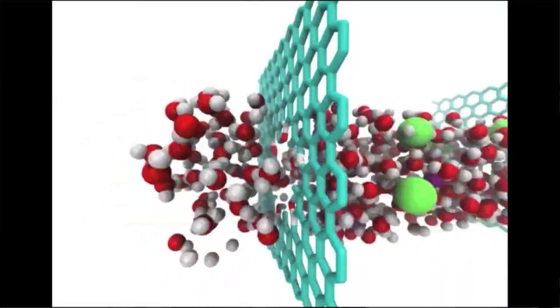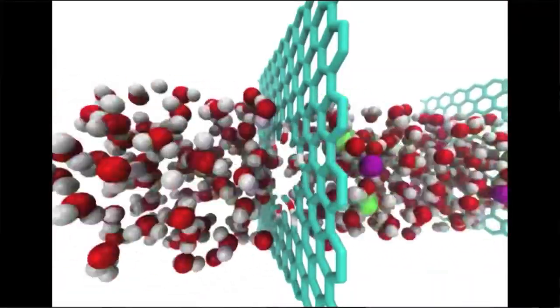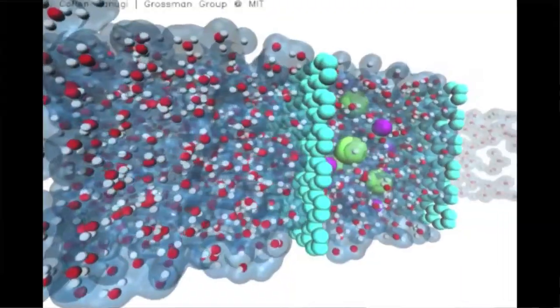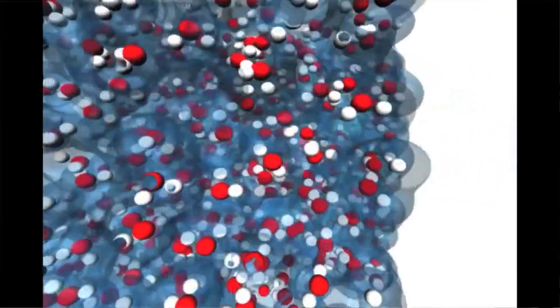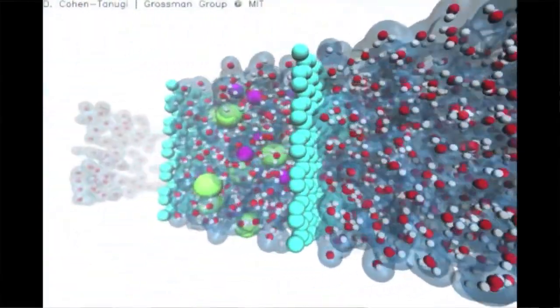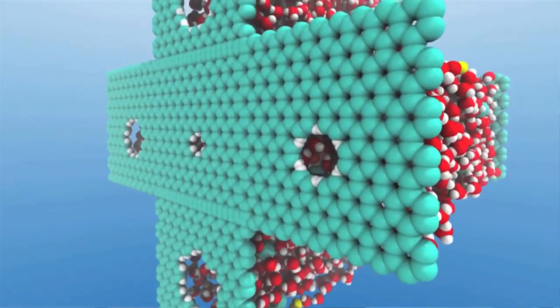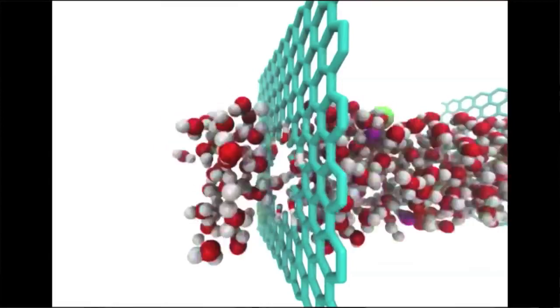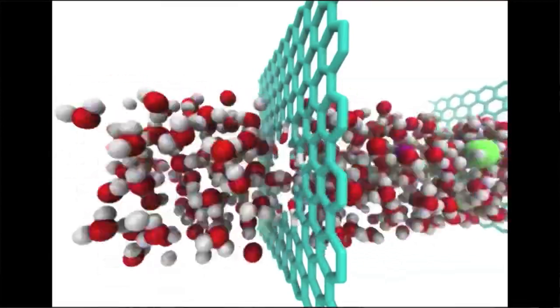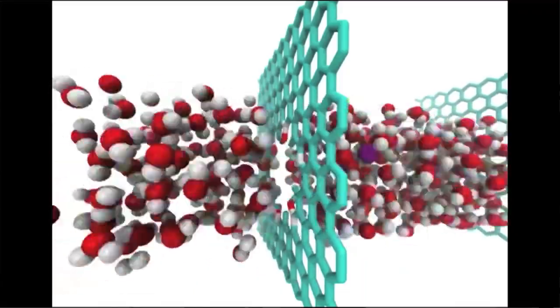Graphene oxide was shown by Rahul in the physics department here to have high permeability to water, but to be an effective barrier to all kinds of other things. One of the ideas is to use graphene as a type of nanomembrane or filter. And that harnesses the fact that graphene is very impermeable. Even very light gases don't pass through. And that means that if we were able to tailor the size of the pores within the graphene lattice, it might be possible to produce a very selective filter, or perhaps use smaller graphene sheets and use the pathways in between the sheets in order to tailor the porosity or the permeability of the membrane.